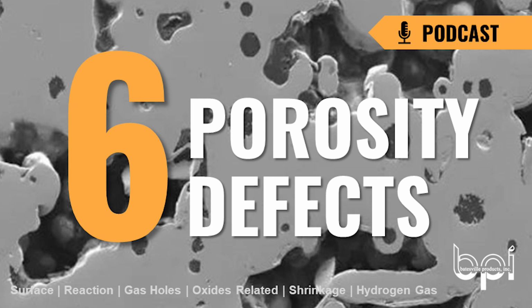Typically on a 356, if you have a 2.59 specific gravity where you measure your reduced pressure test sample, a sample solidified under vacuum, if it's 2.59 or higher, you're not going to have hydrogen porosity in your casting. If it's lower than that, you can. And the farther lower it gets, the more hydrogen that will be in there. But if you wanted hydrogen gas in the casting, to reduce that shrink as we talked about earlier, you might say, okay, I need to run in a range of 2.46 to 2.50. And that's where using specific gravity is the best way to evaluate the amount of hydrogen that's in your molten aluminum.